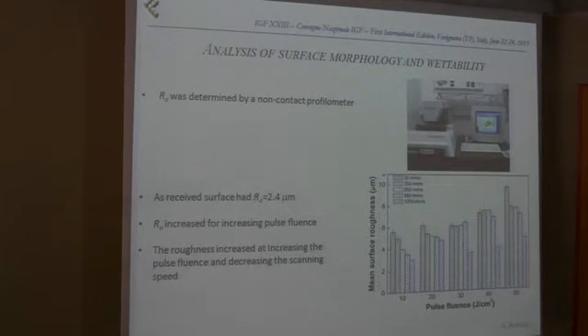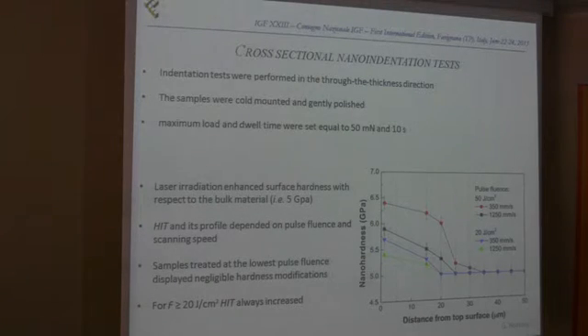As for the contact angle that we saw before, we can say that this kind of surface is maybe following the Wenzel regime of wetting. And once again, the pulse fluence seems not to affect the change in surface roughness so much. Of course, we want to monitor both, because it's important to have not only a chemical interaction between the surface and the adhesive, but also a mechanical one. So of course, if we increase the roughness, we can improve the mechanical interlocking effect during the debonding process.